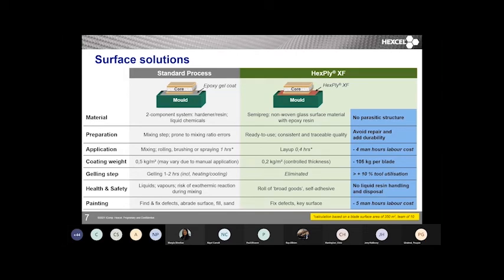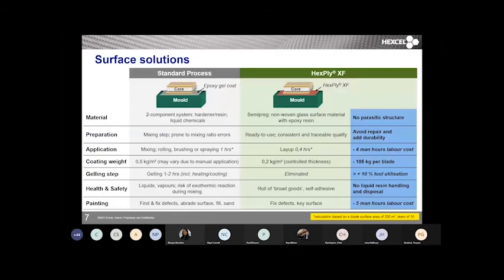You've got a quality improvement in the preparation that you don't have to mix, meter and apply gel coat. And there will inherently be variability with that. A change in the thickness of the gel coat in some part of the blade will affect the overall weight of the blade and the balance of the blade. The reduction in labour is really significant. Even saving 10 minutes, if you've got 14 people in a blade, will massively reduce the overheads. We talked about the potential time saving in moving straight onto layup.